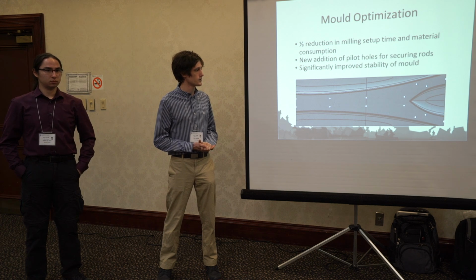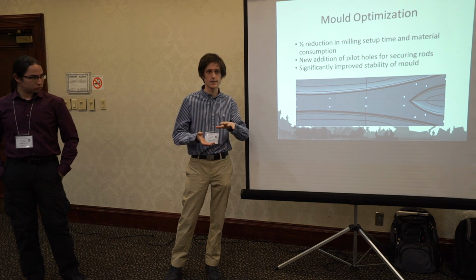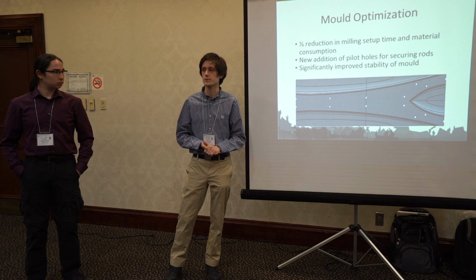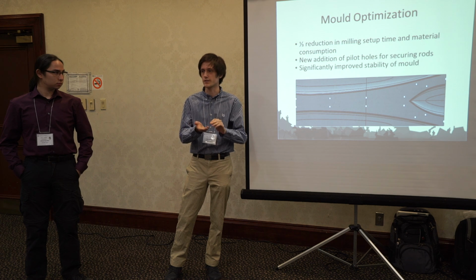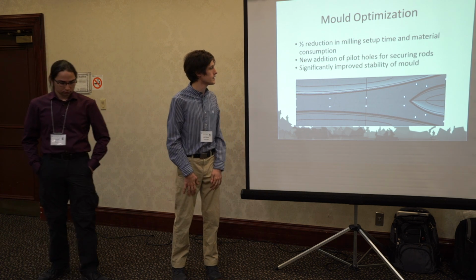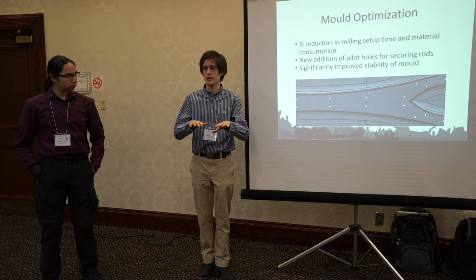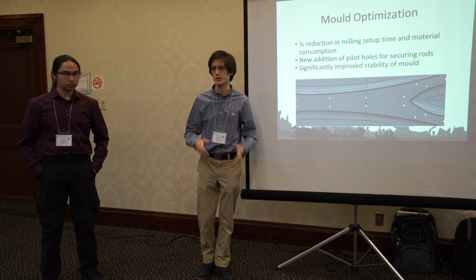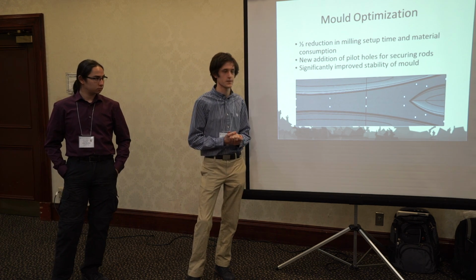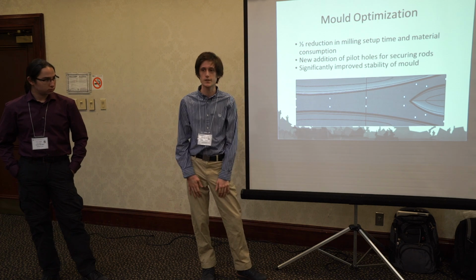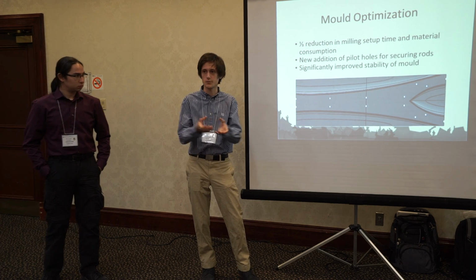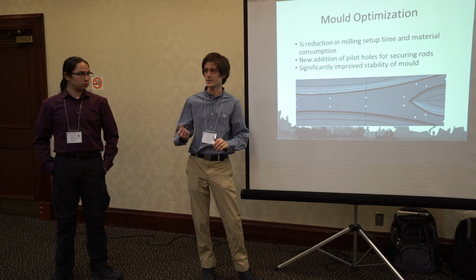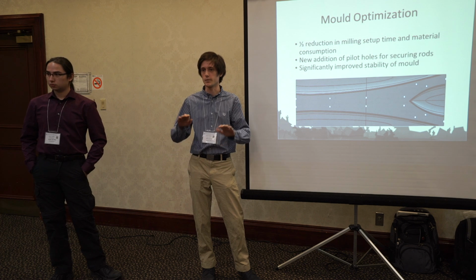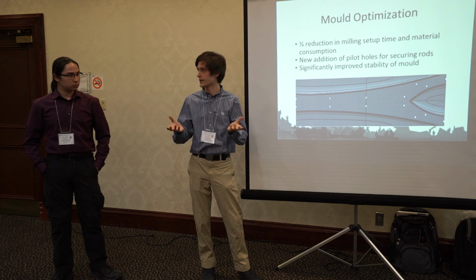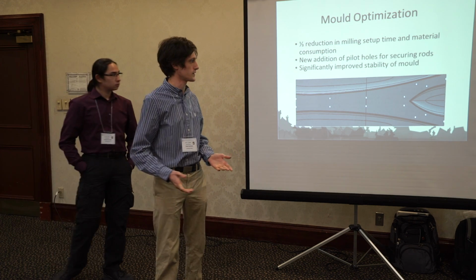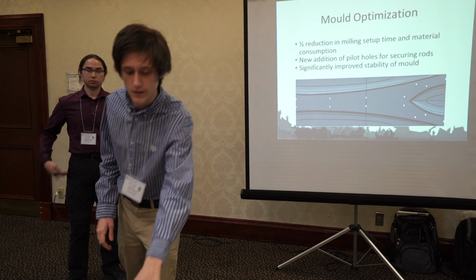On top of this, with the new mill design, we've had problems in the past of the styrofoam not layering on top of each other properly, which causes cracks to form within the canoe as we layer up the concrete. So what we've done is we've put in pilot holes, which when we layer up the milling styrofoam, we can put pipes through, which holds it in place. One of the problems which we've had this past year is that we just cut it straight down through the styrofoam, which allowed that connection to move side to side. We solved that by putting in a massive bolt going through the middle of the styrofoam. But this coming year, we're hoping to layer up the concrete in a way that bricks work to keep it in place and put a pipe straight through that. So hopefully the structural integrity of the mold is going to improve significantly this coming year.